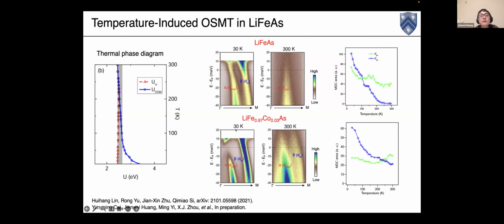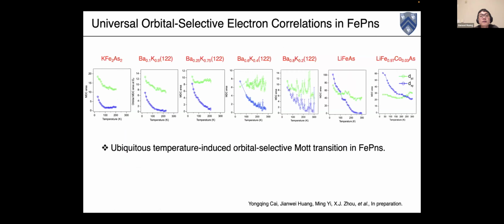And let me end this part by giving you an overview of all the experiments we have done in the iron pnictides. We actually find that these orbital selective electron correlations are also universal, and almost all the compounds, all the parent compounds and the hole-doped compounds, exhibit these temperature-induced orbital selective Mott transitions, except the electron-doped compound.